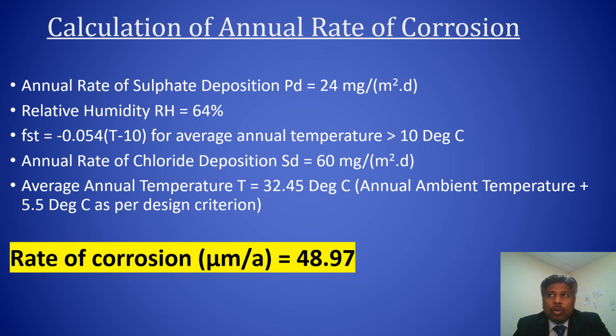We also followed the design philosophy and the principle in that project where they increased the annual temperature to be on the conservative side. The average annual temperature was in the high 20s, closer to 27, 28. But we added an additional 5.5 degrees centigrade in our design calculations. We also looked at the relative humidity from the meteorological data that was available, and we applied it to the formula that was available in ISO 9223 and arrived at a rate of corrosion of 48.97, almost 49 microns per annum.